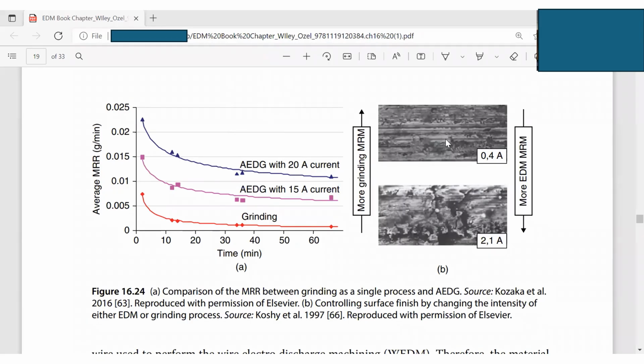Here is more grinding MRR. Here is more EDM MRR. Controlling surface finish by changing the intensity of either EDM or grinding. If you have more EDM, the surface is not good. With more grinding, this is better.